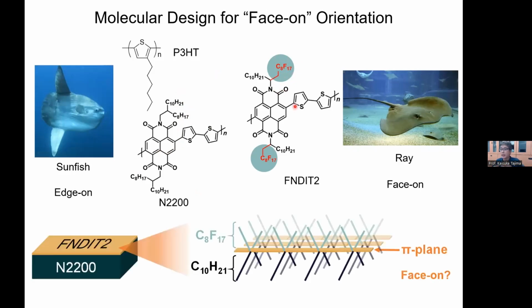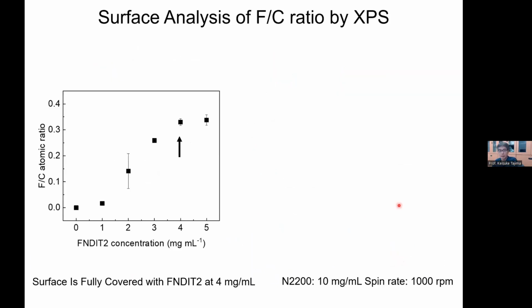Then we can expect that the fluorinated chain tends to go to the surface, right? And then the alkyl chain sticks downward. So this orientation allows, because this is directly attached to the polymer backbone, this polymer could be face-on. That is what we thought about how to control the face-on orientation. It's not a perfect orientation, I would say, but it works.